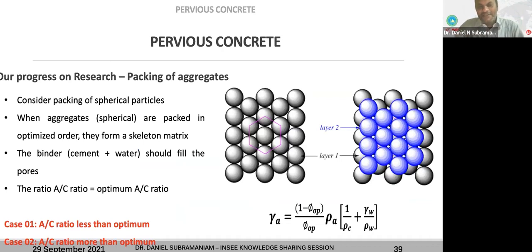Okay, and after that, the next thing that we really need to identify in pervious concrete, compared to conventional concrete, is the aggregate packing. Because in a conventional concrete, the pore space will be filled by the matrix, the fine aggregates and the binder. So you're definitely going to have some kind of support in all directions. But if you take porous or pervious concrete, it is very much a skeleton. So the skeleton must depend on the aggregate packing, right? So any kind of particle packing. Now, in this case, we can talk about binder coated aggregates. Each sphere can be considered a binder coated aggregate.